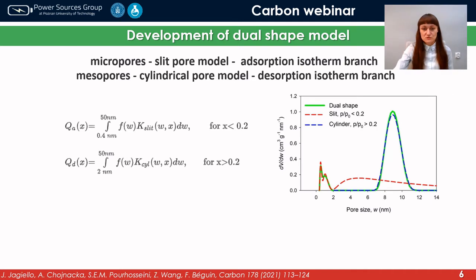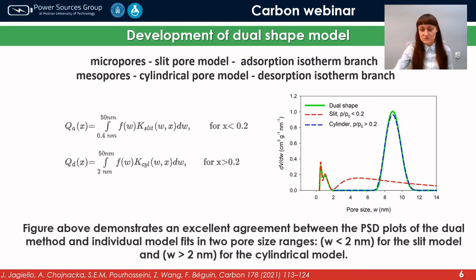Additionally, to verify our approach, we calculated the pore size distribution using the dual shape method. It is represented by the solid green curve, and compared to the pore size distribution calculated independently by the individual slit pore model, which is represented by the red dashed line, and the cylindrical pore model, which is represented by the blue dashed line. And as you can see in the presented picture, we obtain excellent agreement between the pore size distribution calculated by the dual shape model and the pore size distribution calculated by the individual models in the region of the micro and mesopores.